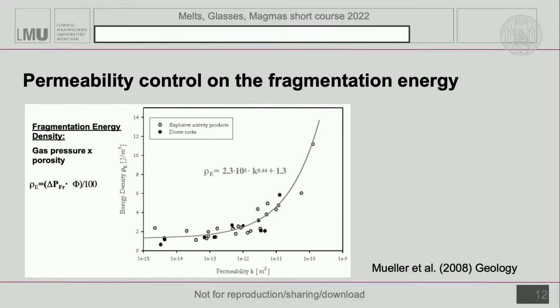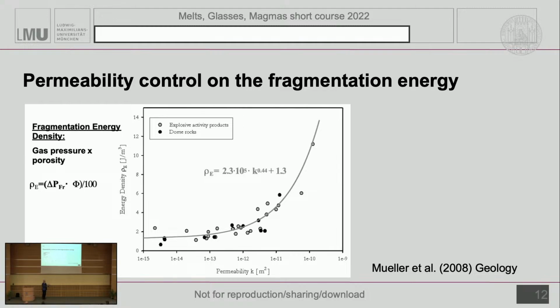It's basically the PV energy, the volume of the bubbles in the rock times the pressure of the gas inside of them. And we see that it's a constant as a function of permeability at low values of permeability, 10 to the minus 15, 14, 13, but it starts to be a variable when we go to high values of permeability. So what we can do is divide the world up here in the middle into an area where a certain value of the energy density corresponds to the fragmentation of the rock, because the gas is immobile, because the permeability is low.